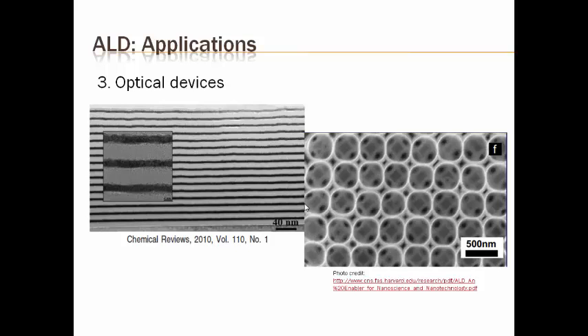A three-dimensional photonic crystal may be fabricated using ALD. Photonic crystals are structures made of periodic dielectric materials which can modulate and manipulate light, so they are being researched to be used in future optical computers. This photonic crystal was made in a common process: a crystal array of silica spheres was fabricated, tantalum oxide was deposited between the spheres by ALD, this was converted to tantalum nitride in the presence of ammonia, and the silica spheres were dissolved in hydrofluoric acid to leave behind this beautiful photonic crystal structure. Similar principles have also been used in biomedical applications to get an intricate exoskeleton model of an insect as a research tool.